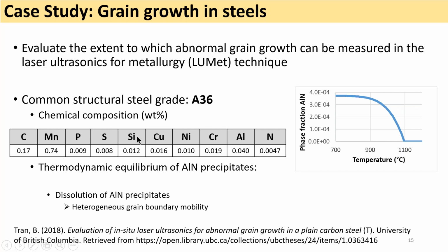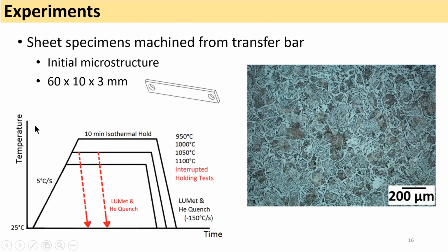And in this alloy, what's important to notice is that there is aluminum nitride precipitate, which tends to dissolve around the temperature of 1100 degrees. This dissolution of precipitate, which occurs simultaneously to the austenite grain size, will have an impact on the way the grain growth will occur, as we will see. So the test schedule is indicated here. It's a typical heat treatment for austenitization: go to high temperature, stay for a little bit, and then go down.